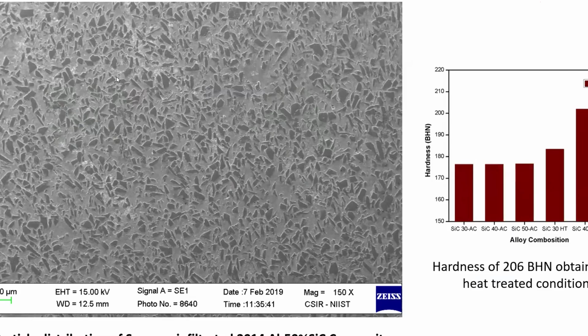So here we can see that the particle size is very much finer, and it is very well distributed throughout the matrix. You can see the 2000 series of alloys, and you can also see that the heat treatment shows that as you increase the particle size, the hardness also gets increased. And this can be used for a variety of applications, starting from armors as well as in thermal management.